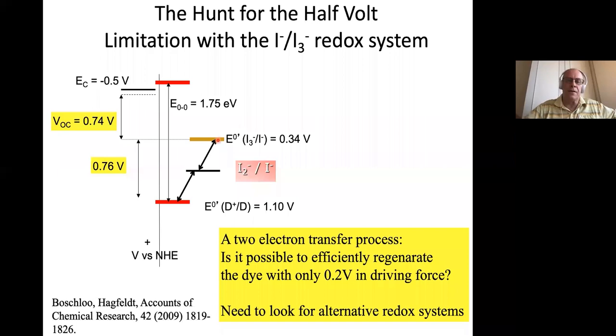And when people tried all other kinds of redox couples, that was the problem. And the way to fix it would be to passivate the surface here, so you avoid electrons from TiO2 reacting across the interface. So people tried that, and you think about making maybe some insulating oxide, like aluminum oxide, zirconium oxide, passivating molecules, so this cannot happen. But it really was not successful to introduce a new redox couple instead of iodide, triiodide.